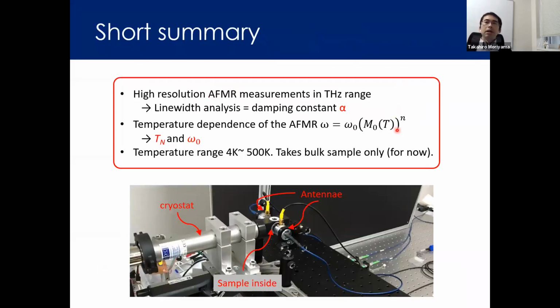So I just want to make a short summary here. In our system, we can do the high resolution antiferromagnetic resonance measurement in the terahertz range. Since it's a high resolution, we can see the line very well. We can do the linewidth analysis, and from that we can derive the damping constant alpha. And from the temperature dependence of the resonant frequency, we can also derive the Néel temperature as well as the intrinsic resonant frequency. For now, this system can change the temperature from 4K to 500K. And for now, we can only take a bulk sample because this is an absorption measurement. We need some volume. We are trying to do the thin film measurement, but it's not successful so far.